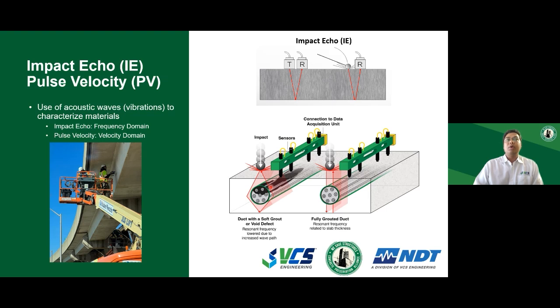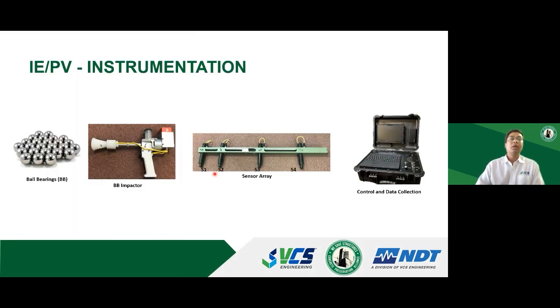Our device can do impact echo and pulse velocity both at the same time, but when it comes to post-tensioning applications, we more often rely on impact echo than anything. In terms of instrumentation, as I had mentioned, we use a pneumatic impactor. We use steel ball bearings to make the impact on the concrete surface above the tendon. And then we have a sensor array which has 4 sensors which are waiting for the reflections to come back, and that will give us the data.